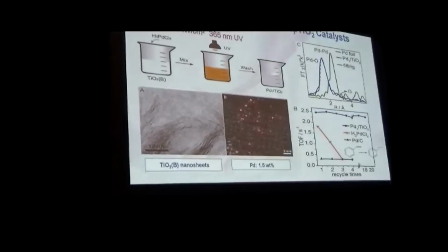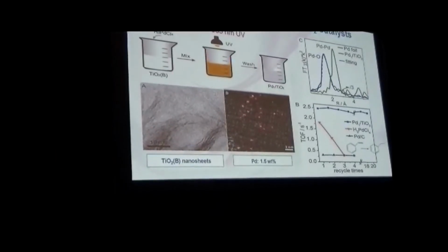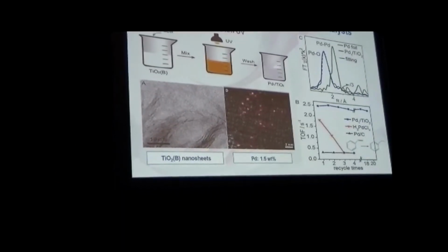But you can make it, and here's the HRTEM. We can see the dots, single atoms. Here is the substrate. We have no Pd-Pd bond. And the single atom catalyst shows a very high hydrogenation rate for the C=C bond.